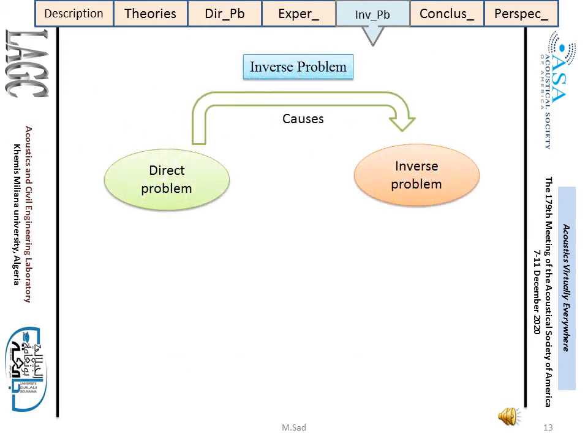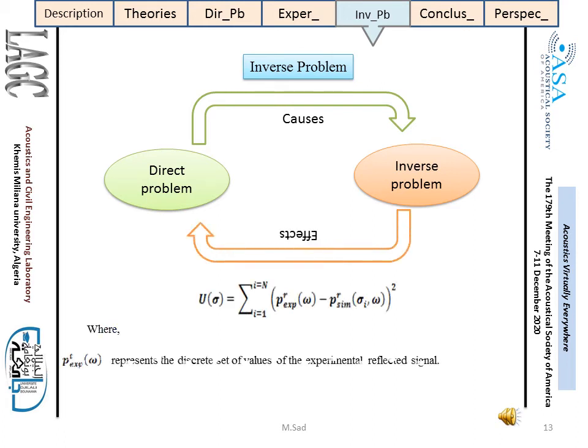The direct problem consists in constructing theoretically the transmitted signal knowing the incident signal and the parameters of the medium. Given the experimental incident signal and the transmission coefficient, which plays the role of transfer function of the medium as a function of the parameter to be found, we deduce the simulated transmitted signal, which must be compared to the experimental transmitted signal. The inverse problem therefore consists in minimizing the difference between the experimental and simulated signals by varying the recurrent parameter. The solution corresponds to the set of parameters that give the minimum deviation between the simulated transmitted signal and the experimental one.